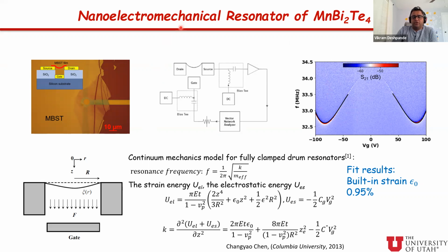In short, we're measuring the RF transmission through the sample, and we're looking at this as a function of various parameters. The RF transmission essentially peaks at frequencies that correspond to the mechanical resonance of these samples, as you can see, for example, in this transmission measurement as a function of gate voltage and frequency.